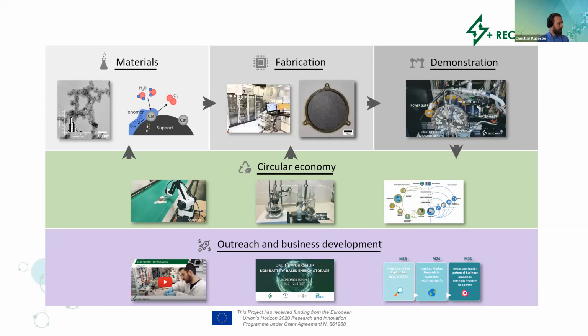A big part of material development here is, of course, also material testing, which Aline will talk about in a moment. We also look at how to fabricate materials, fabricate the catalyst. We want to be able to produce at least 50 grams an hour using flow synthesis. Then we look at how to fabricate the catalyst inks that we are using to deposit onto electrodes to produce membrane electrode assemblies. They are tested in single cells, and these MEAs are then also integrated into the stack where we stack several MEAs together to produce hydrogen. The challenge here is to optimize the fabrication process and the inks so we can really utilize the catalyst activity that we have achieved.